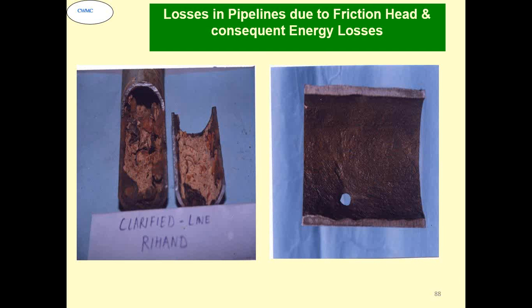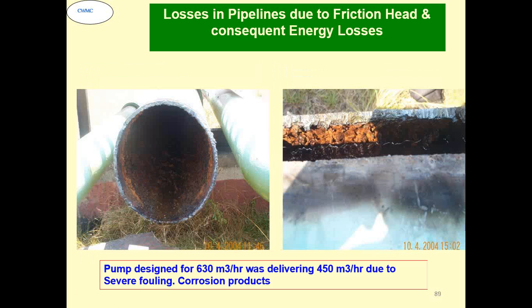Typically you can see microbiologically induced corrosion and fouling, and below that the whole cause in the pipeline is the corrosion below that. Now this pipeline what you see here is a main pipeline which is supposed to supply cooling water to a 630 meter cube pump, but it was not able to deliver more than 450 meter cube due to the severe fouling and corrosion in the pipeline. Ultimately this pipe was replaced by an HDPE pipeline.